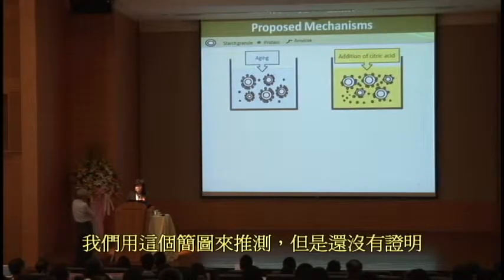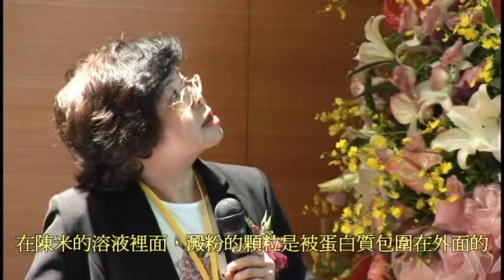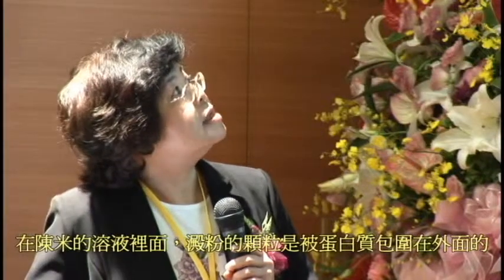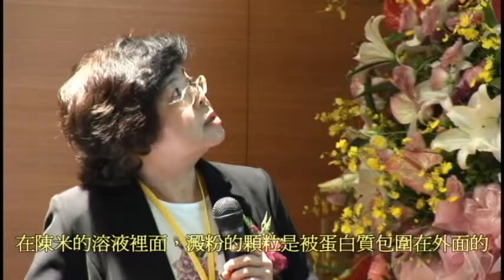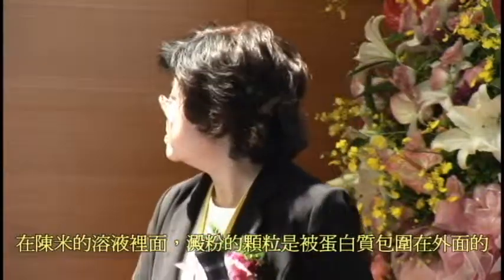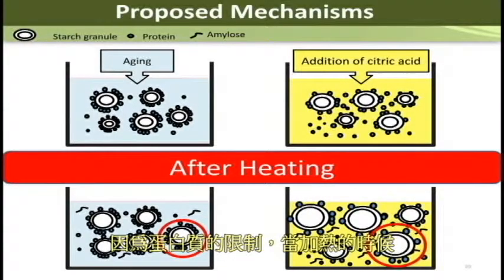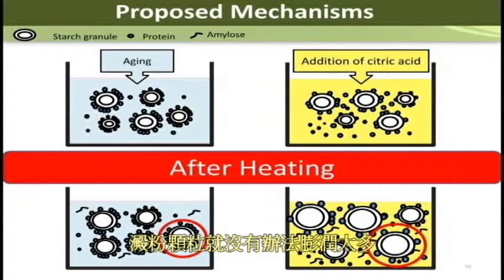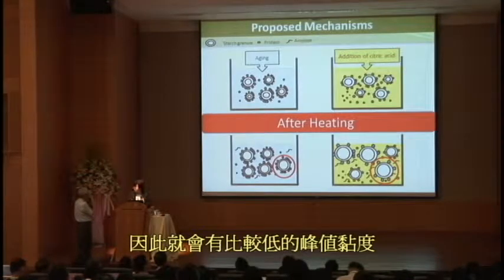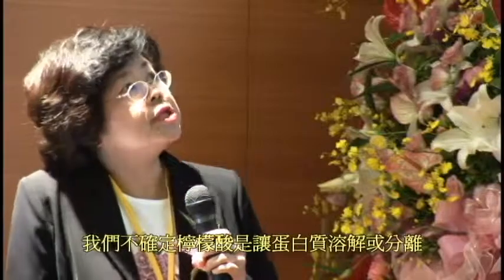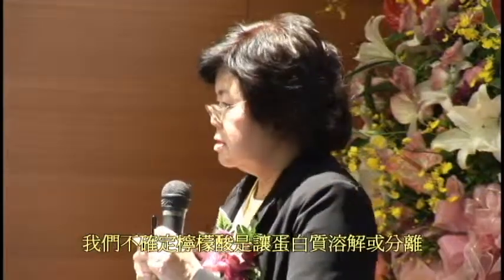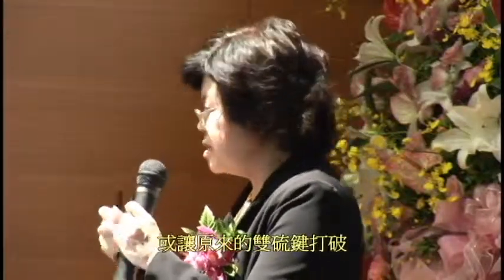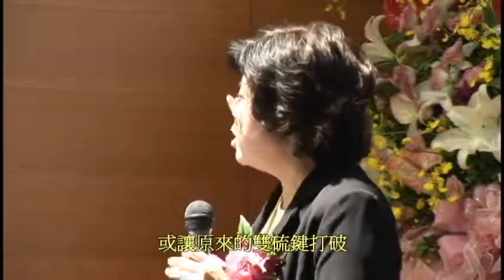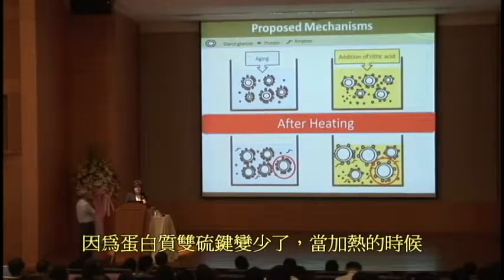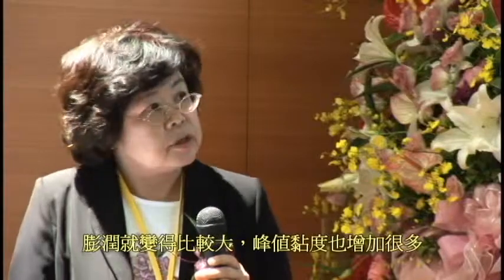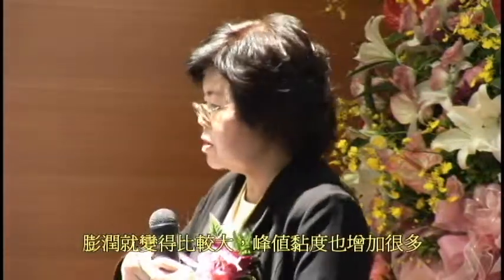This is a simple schematic of what we think, but we haven't proven it yet. This is a rice starch granule, and this is the protein. For aged rice, there is protein surrounding the granule, linked by disulfide bonds. So if we bring the aged rice to heat it, after heating, the granules swell but not much. That's why it has low peak viscosity. But when we add citric acid to the solution, the citric acid might dissolve the protein, or maybe take the protein out from the granule, or maybe disrupt the disulfide bonds, we are not sure. So with less protein chain, the swelling is increased as shown here, and that's why the peak viscosity increased.